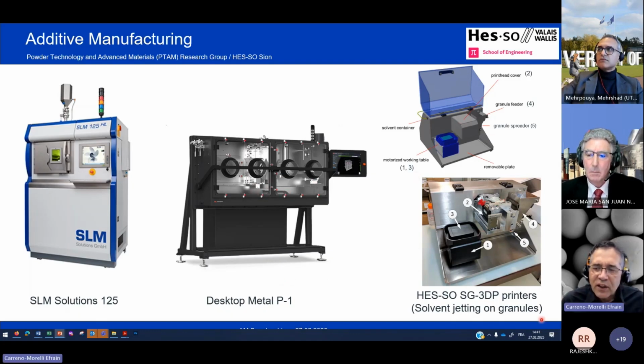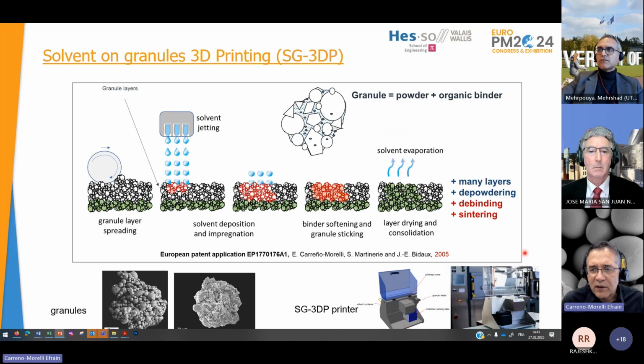We call it solvent jetting on granules, which we developed many years ago. I can provide a description of that. It can be useful to make shape memory and superelastic materials because it offers great flexibility on the base powders. This technique consists in making granules, like you see here. These granules are powder particles agglomerated with the binder, and these particles can be spherical or irregular, and one can include even sub-micron powders, nano powders, if one likes.